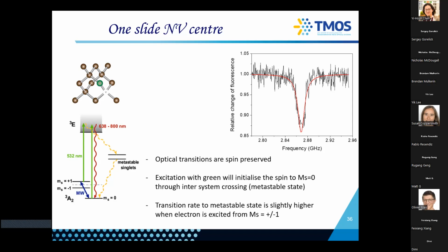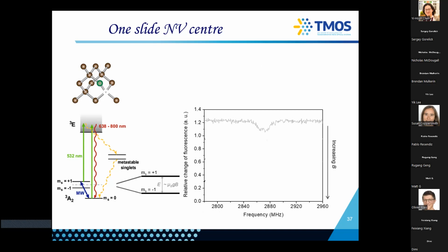And so this reduction in luminescence is called an optically detected magnetic resonance. It's basically an optical EPR. Okay, so it tells you exactly which spin state your system is prepared in. And of course, like EPR, you can also apply a magnetic field to split these levels, the plus and minus 1. 0 obviously stays at 0.